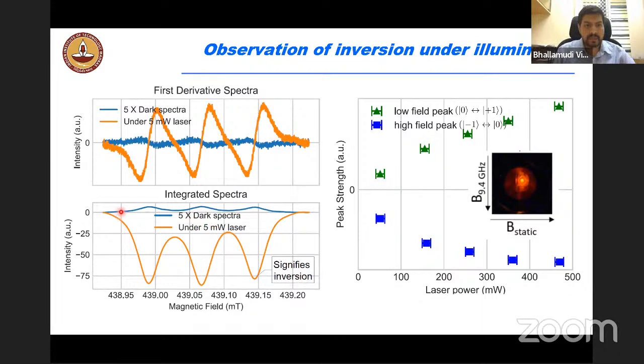So the spectrum is much smaller. As you can see, we get a huge signal when we apply the green laser and polarize our spins, and also the sign inverts for the 0 to -1 transition. For the other transition, it does not invert. So we can create a spin inversion. We have been able to verify it, and we are in the process of studying this signal more thoroughly, and we are hoping to wrap this work up soon, but this is where we are presently.